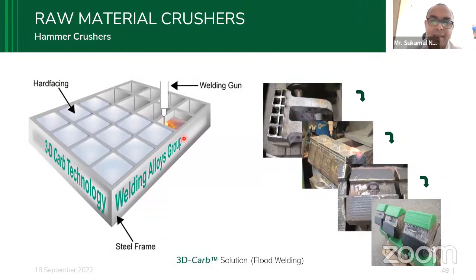And this is basically our 3D-Carb, which is our unique solution and patented product, to be honest with you. So this is the crusher's hammer. We take it back, and then this is the layer we put. And you can see that we do not do complete welding in this way. We make small squares and deposit them so that it can enhance the life of the component. And this is a trademark product. It's our own developed technology in France.